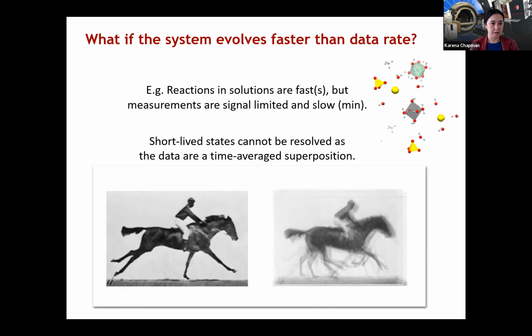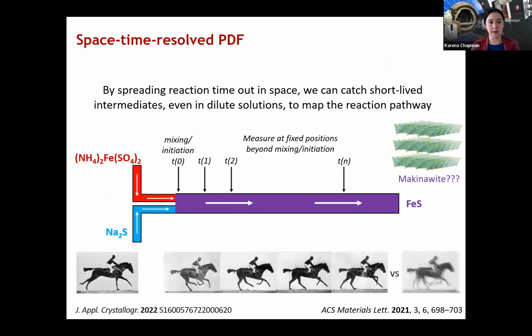To address this challenge of faster time resolution reactions, we took advantage of the property of solution reactions that they flow. We can spread our reaction out in space by flowing our reactions, mixing two reagents, initiating that reaction, and continuing to flow that reacting solution along a flow capillary. If we put the X-ray beam just next to that initiation point, that tells us about the early stage of the reaction, and we can sit there as long as we need to accumulate data for quantitative analysis.